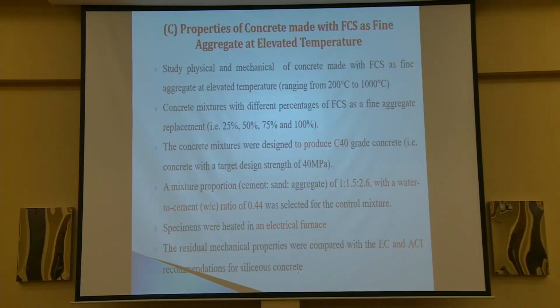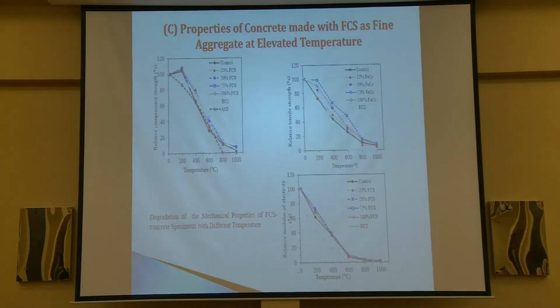And then we studied the behavior of the material at elevated temperatures, at high temperatures, and we heated the specimens up to 1,000 degrees Celsius. And also we find that the behavior is comparable to the normal concrete, and we compared the degradation of this material with the degradation of concrete properties in EC2, European Code 2, and also the American Concrete Institute. And we found there is a good agreement, which is matching of the degradation properties of this material.